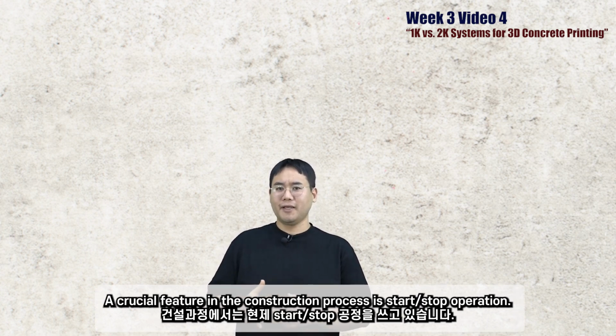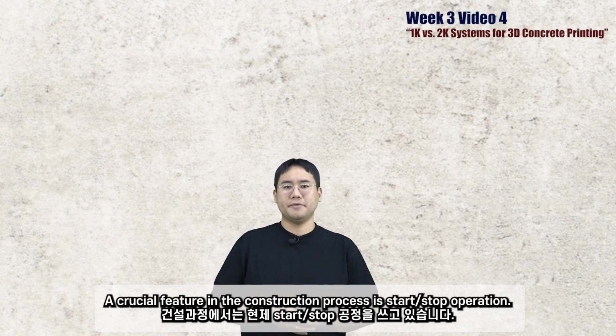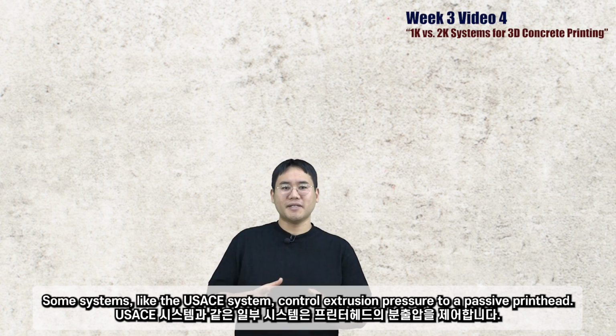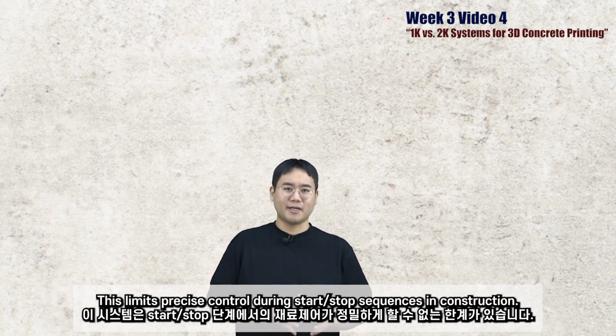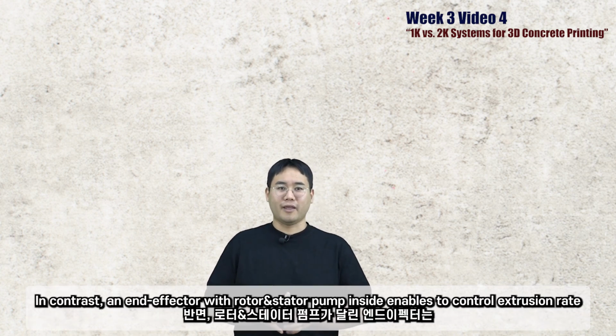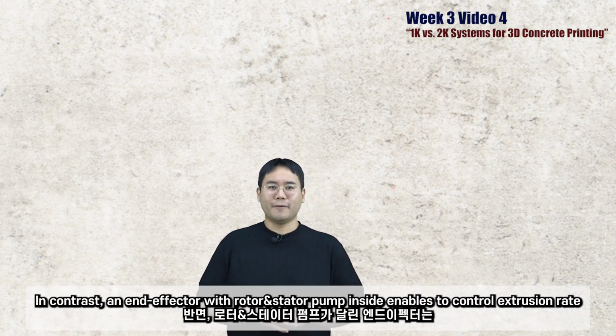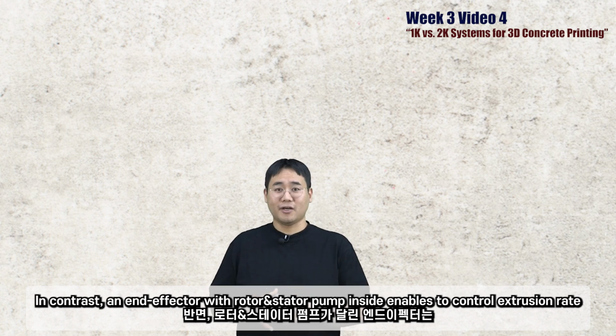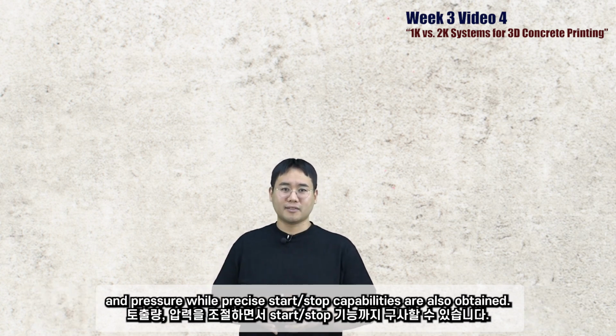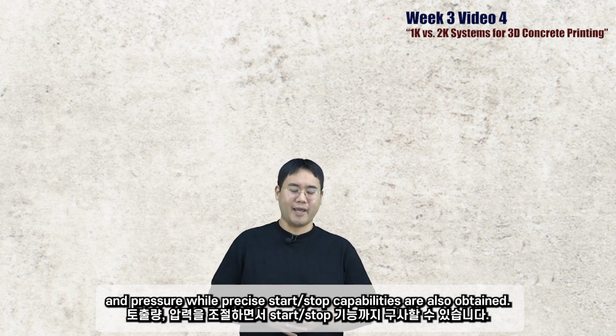A crucial feature in the construction process will be the start and stop operation. Some systems like the USACE system actually control extrusion pressure to a passive printhead. This limits precise control during start and stop sequences in construction. In contrast, an end effector with a rotor-stator pump inside enables control of extrusion rate and pressure, while precise start and stop capabilities are also obtained.